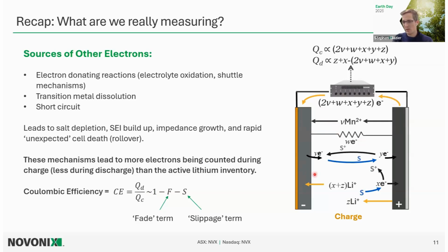So as we charge the cell, we're counting all these extra electrons. When we discharge the cell, we actually don't count any of these things because they're all self-discharge mechanisms. So we actually miss out on counting them, and they will discharge our cell slightly. So what this means is this is another term that contributes to our coulombic efficiency. Coulombic efficiency doesn't just have to do with capacity loss, it also has to do with added electrons and missed electrons due to self-discharge.